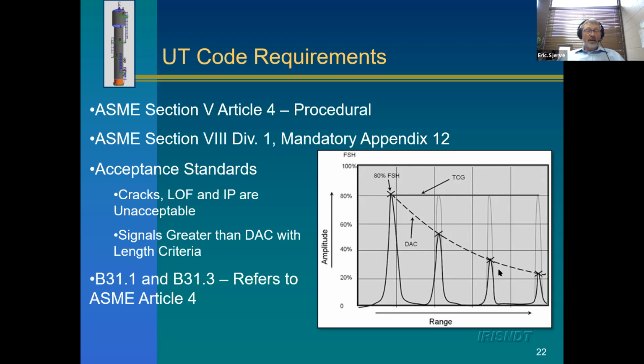Now, ASME Section 8 has the acceptance criteria for ultrasonic testing, and I put it down here. For ultrasonic testing, whenever a technician finds a crack, lack of fusion, or incomplete penetration in a weld, it's unacceptable. Those are all stress risers, and they all need to be repaired. And then for volumetric defects like slag and porosity, signals greater than DAC with a length criteria are rejectable. And that comes out of ASME Section 8. And then, like the other examples, B31.1 and B31.3 refer back to ASME Article 4. So those are the piping codes.